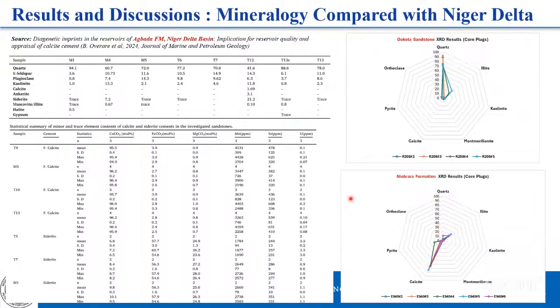And if we compare this with a Niger Delta reservoir in terms of quartz content, this is a study from Overare et al. 2024. You can find out that both have clay content variation, they don't have the same, but both can be categorized as quartzose sandstone. But the feldspar contents are different, and the clay content is also different. That is what we observed from the experiment that we have.